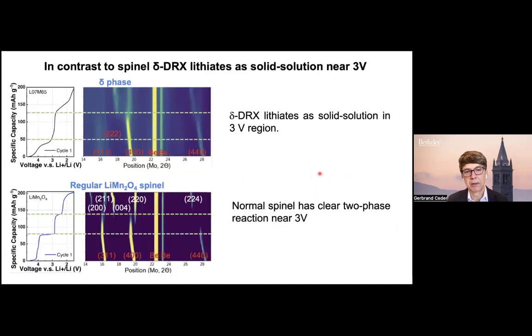In contrast, if you look at this transformed material through cycling, which we refer to as delta, if you do in situ diffraction, you see something very different. So again, this is a regular spinel. And when you cycle a regular spinel through the 3-volt plateau, you clearly see this peak splitting, right? Which is reminiscent of the two-phase reaction. You have a new peak appear and the old one disappear. On the other hand, if you look at what's called delta DRX, you have a continuous change in peak position. So even though it looks like a plateau, this is clearly lithiating and delithiating as a solid solution.